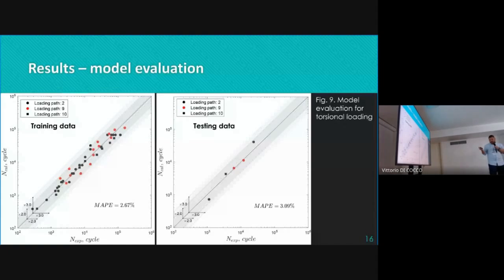Obviously, it was random, so sometimes the 10% were not from every single path, so we tried to review it to get results for at least 1 to 2 specimens of each path available to fact check. We did it 12 times for this process only. So I will show you.